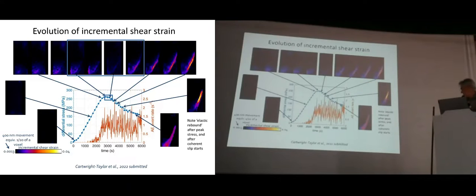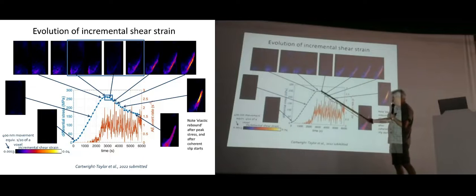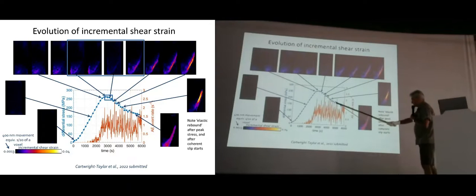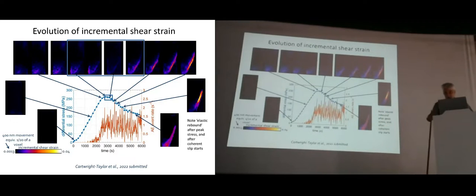And then once the fault exists, once you've actually got frictional sliding in between these 2 images, then again, you see another relative relaxation of the strain rate. So we see 2 relaxations, one just after peak stress, and one after the fault has been formed, when we can draw a line from one side of the sample to the other through contiguously broken elements.